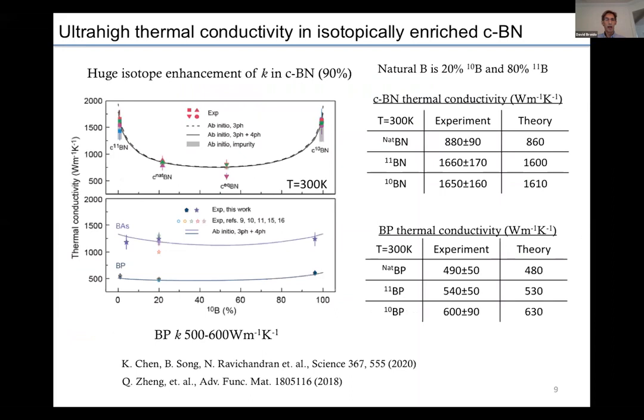Okay, I mentioned these 2 boron-based materials, cubic boron nitride and boron phosphide, on the first slide of my talk, and I want to come back to those now as we've been involved in research on these 2 compounds. Cubic boron nitride is similar to diamond in being composed of light atoms and having strong bonding. And so one might think from the conventional criteria, its thermal conductivity should be as high as diamond, but in fact it has a large isotope mixture on the boron atom, 20% boron 10 and 80% boron 11. That large isotope mixture presents as random mass fluctuations that scatter phonons and lower the thermal conductivity.